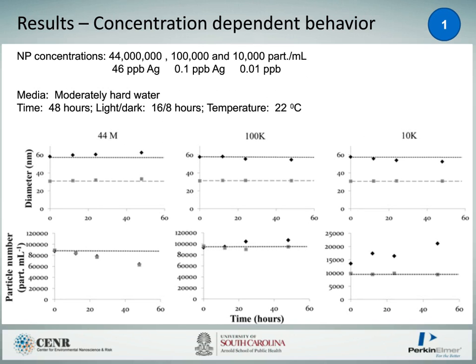So I'm going to go through some results on concentration-dependent behavior and why this is important. Traditionally, when we look at transformations in media, we're looking at around 50 to 1,000 ppb of your mass concentration of your contaminant. We go at these high levels because it's very difficult to actually look lower. The equipment that we used previously was unable to go lower in concentration than this. Single particle ICP-MS has allowed us to go lower, so in this case we've also used 100,000 particles per mil and 10,000 particles per mil, which is 0.1 to 0.01 ppb of silver. And this is more in the range that we would expect to find in the environment. So single particle ICP-MS has actually allowed us to go to these environmentally relevant concentrations.